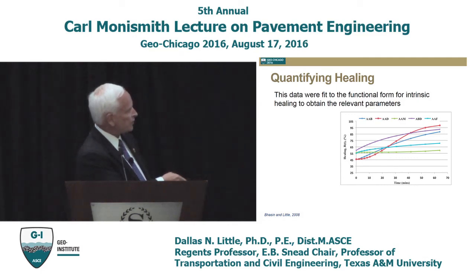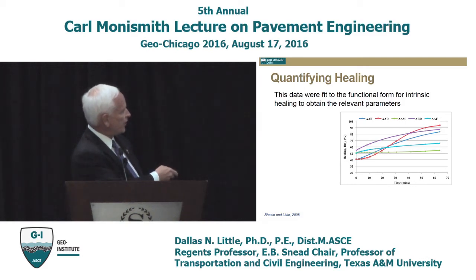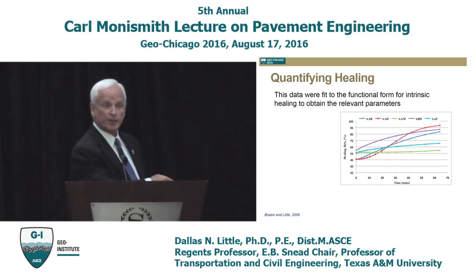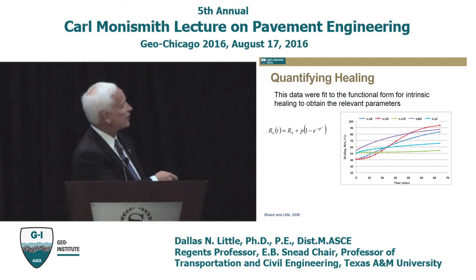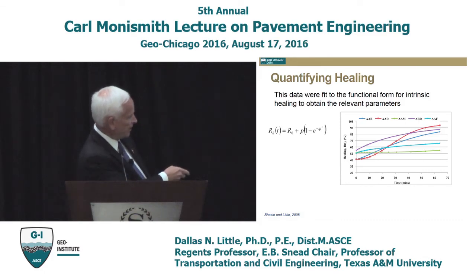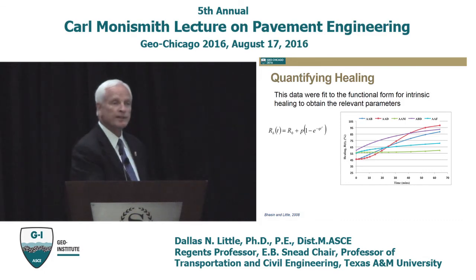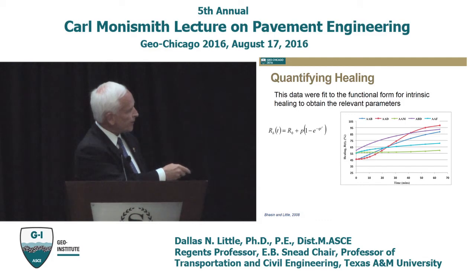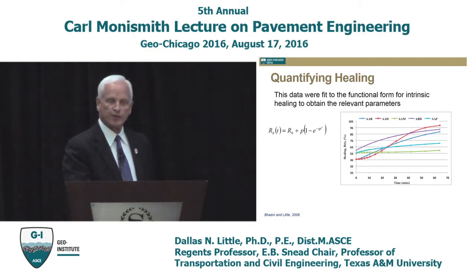But you get an initial response, which is right here, which is pretty substantial, and then you get a time-dependent response. And if you come up with a general equation for that recovery of strength, this R sub h, you have the initial component, R sub 0, and then you have a time-dependent component, sort of a sigmoidal relationship, e to the power minus q times t to the r power. So you got a sigmoidal healing recovery process that's time-dependent. So this has to do with wetting, one would think, and this has to do with the reorganization of the molecules to lower the free energy.